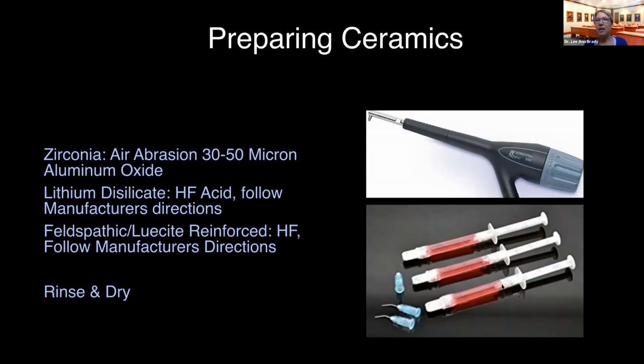Zirconia is a different thing. There are 3 big categories of zirconia: 3Y, 4Y, 5Y. You don't need to remember that. The general rule is the prettier it is, the weaker it is, right? So the more aesthetic the zirconia, the more translucent the zirconia, the weaker it is. Most of us use zirconia because we want a high strength material. We want something higher strength than lithium disilicate or Emax. There's no place on a laboratory prescription I've ever seen to specify whether you want high strength zirconia, middle strength zirconia, or highly aesthetic low strength zirconia. You need to call your lab and have that conversation. Most of the time, they are making that decision for you.